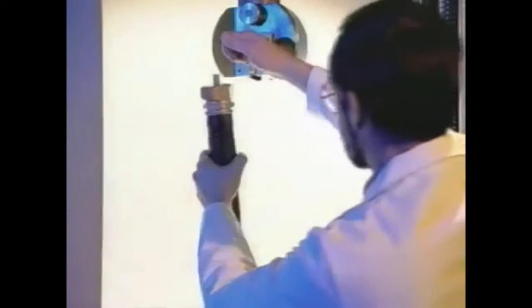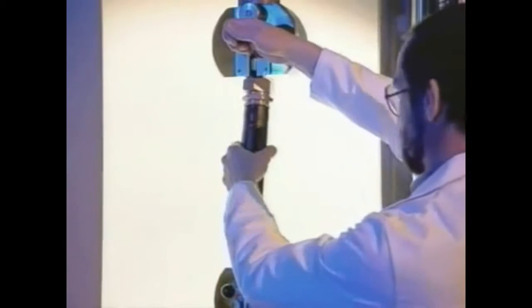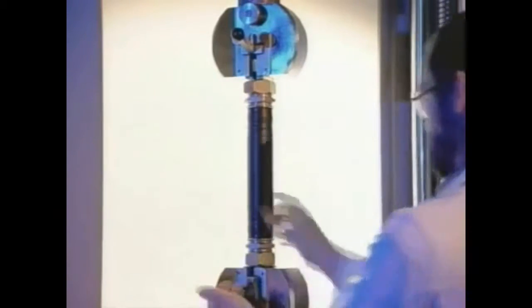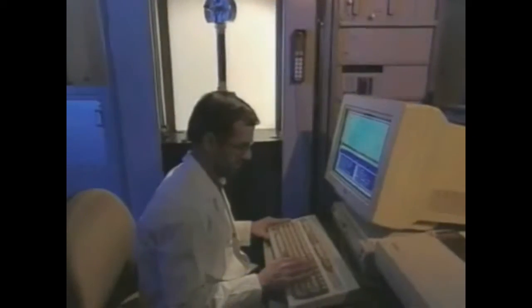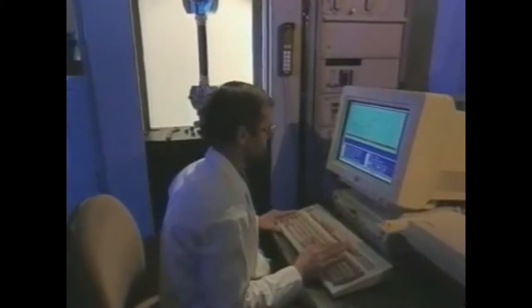Our fitting easily passes the standard test for tensile strength. It was subjected to 3,000 Newton in a vertical position for 1 hour. But how great are the reserves of Geberit Mepla? The test fitting is now subjected to 11,000 Newton for 1 hour. This is equivalent to the weight of a normal plumber's van.